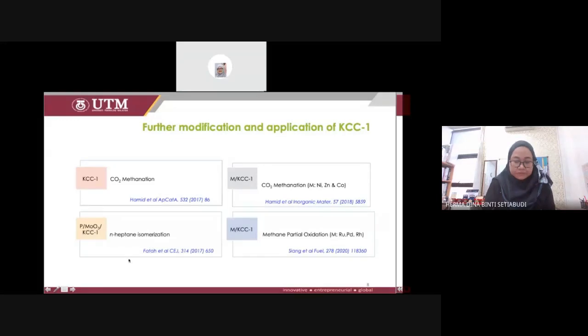Okay. And then we also tried to modify the KCC1 with molybdenum and phosphorus, and then we applied it on the n-heptane isomerization. Okay, Abdul Fattah found that when they mix the phosphorus and molybdenum, bronze formation, the bronze could be formed, which acts as an active site that can enhance the isomerization compared with without the phosphorus. So this combination of phosphorus and molybdenum is very important for the enhanced n-heptane isomerization.